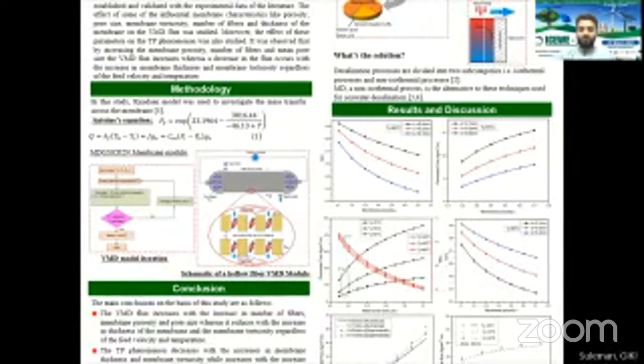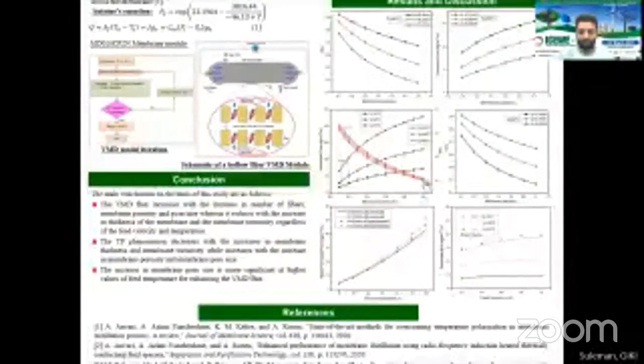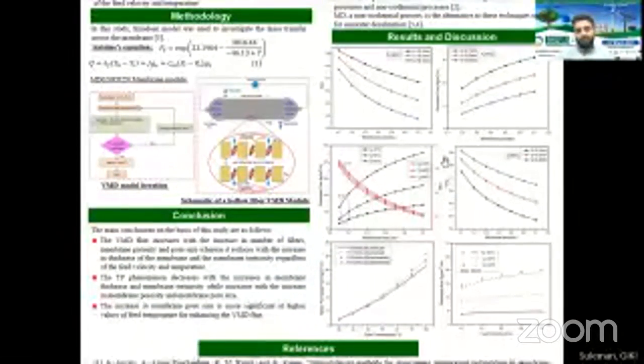We have studied the membrane porosity, the membrane pore size, and the membrane thickness. We have studied their effect on the temperature polarization phenomena and the VMD flux, that is, how it changes when we increase these membrane characteristic parameters. And we have also related our findings with the experimental results based on the feed temperature and the feed velocity.